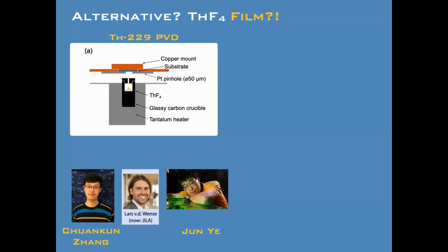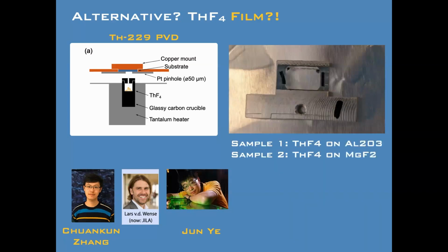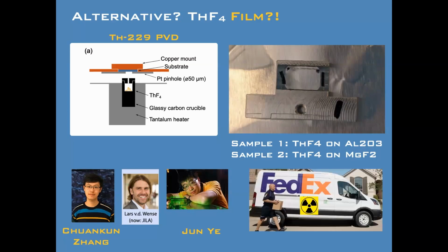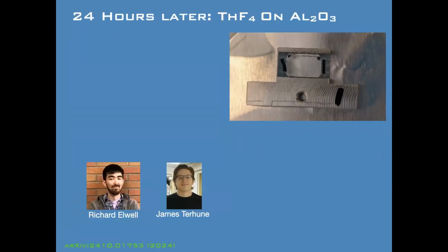Falcone, who's the grad student who I'll mention in a minute, made some samples for us, just coating both sapphire and magnesium fluoride with thorium fluoride. It's a thin film, probably. It's probably not a single crystal, but just like evaporate some thorium fluoride on this. And as you alluded to, FedEx will ship anything. And 24 hours later, we had this at our lab at UCLA.